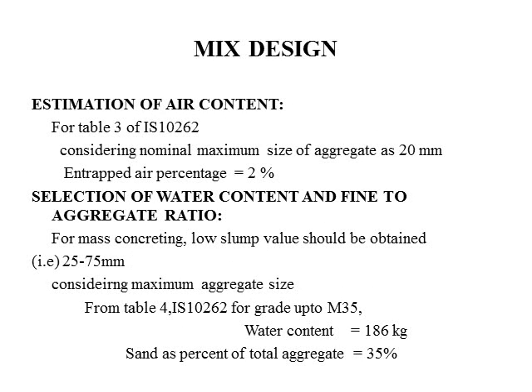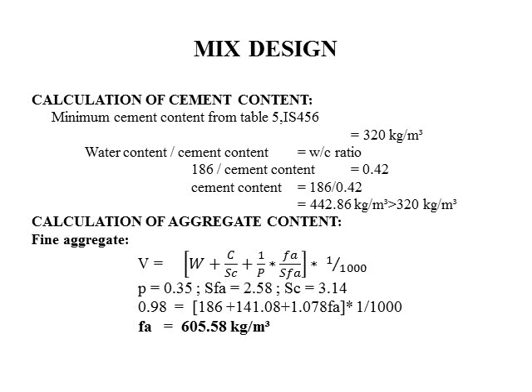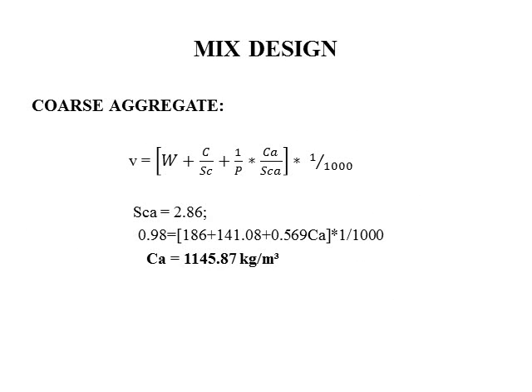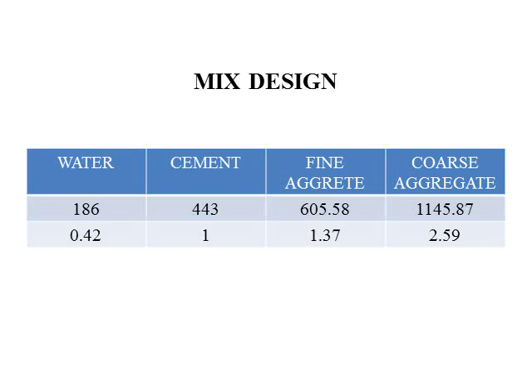Calculation of water content and the cement content. The water content is found to be 186 kg for maximum size of aggregate 20 mm and the sand percentage of total aggregate is 35%. The cement content is calculated to be 443 kg per meter cube. The quantity of fine aggregate was found to be 605 kg per meter cube and the coarse aggregate is 1145 kg per meter cube. The ratio was found to be 1:1.37:2.59 with a water cement ratio of 0.42.